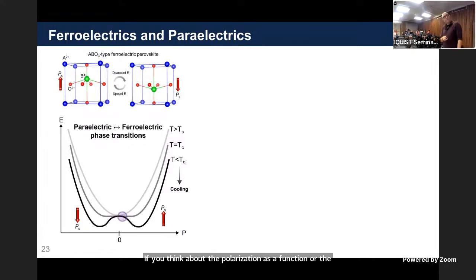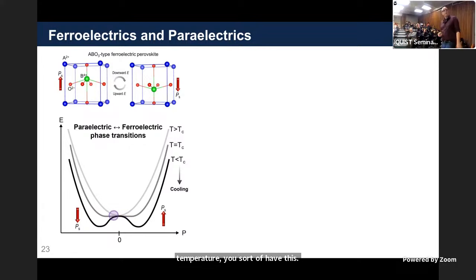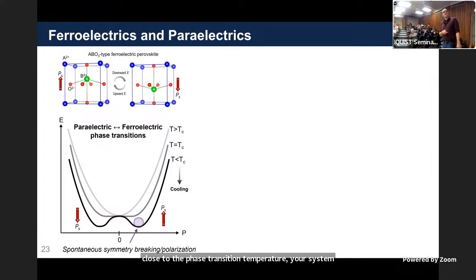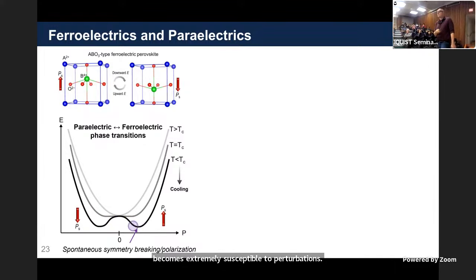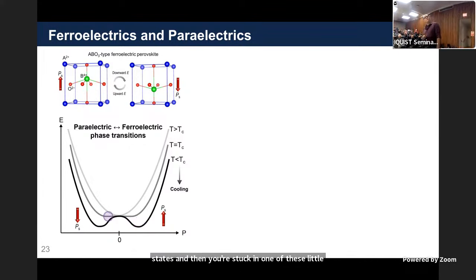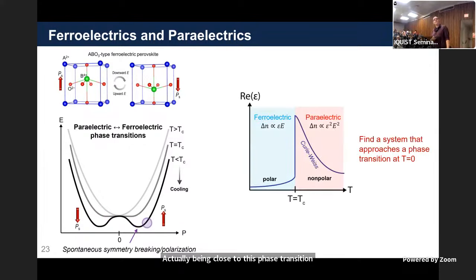If you think about the energy as a function of polarization, above the Curie temperature, you have this harmonic looking nonpolar response. But as you cool close to the phase transition temperature, your system becomes extremely susceptible to perturbations until finally you undergo the phase transition, you drop into one of these macroscopic polarization states, and then you're stuck in one of these little harmonic wells. And so if your goal is to make something that has a high dielectric constant, that has a high susceptibility, being close to this phase transition temperature means that you can have extremely high susceptibility. If you plot the dielectric constant as a function of temperature, as you approach this phase transition, your dielectric constant explodes. And that's really, really exciting.